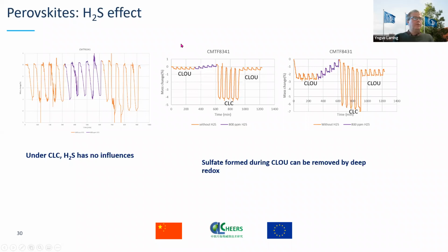When it comes to effect of H2S, we see that when we run CLC, it does not affect the material so much, with the sulfur part really in the middle there, and back to normal condition without sulfur. We say 800 ppm sulfur. If we take out the effect down to argon or inert atmosphere, we see that we get a concentration of sulfur, most likely on the surfaces in this case. But after some CLC deeper redox, it gets back to normal again, meaning that the sulfur can be taken off, and it's not so critical, especially for this compound here.